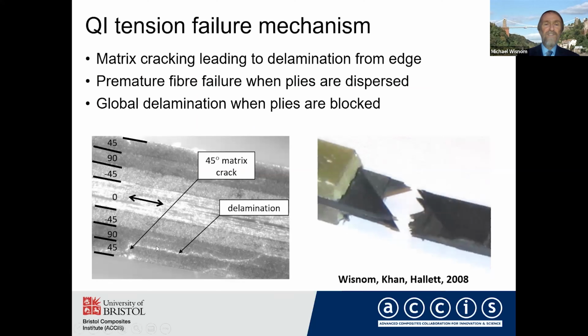So if you look at this specimen here, and this is not the failure, this was taken away. You take a specimen which has failed, and then you look at the edge a long way away from it, then what you see is you have these 45 cracks on the surface, and then the delamination, which is starting between the 45 and the 90, and then that propagates through the thickness. So when the plies are dispersed, that early delamination and transverse cracking results in premature fiber failure. When, on the other hand, you block those plies together, then that leads to a global delamination and the whole specimen failure by delamination. But in both cases, you see a reduction because the failure is starting at the edge and from those transverse cracks.